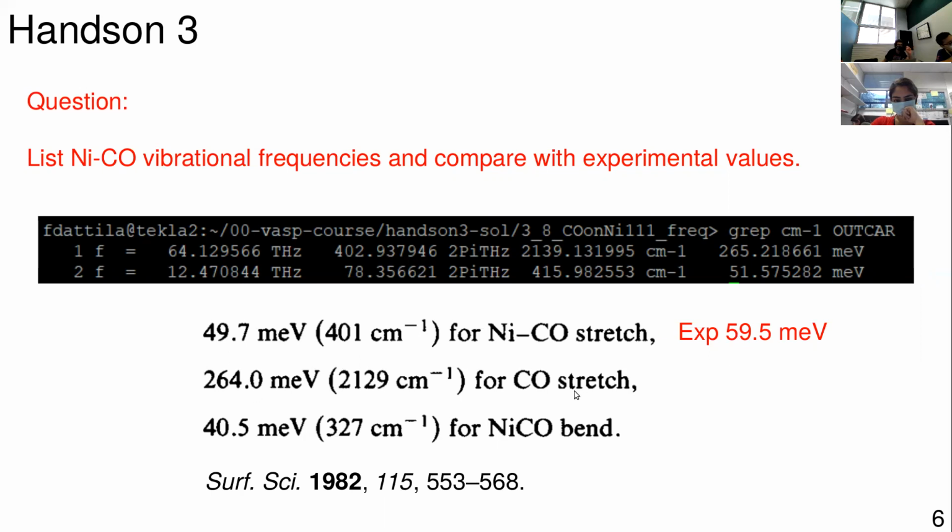And the reason why we don't mimic the experimental value one by one is simply because whenever you have vibrational frequencies, there are some systematic mistakes with DFT. So again, DFT is very valuable and really strong in getting the trend, but it fails a bit whenever it has to give you the absolute value. So you should always be extra careful when you try to compare one by one experimental values with DFT values, because in DFT we have some systematic mistakes.